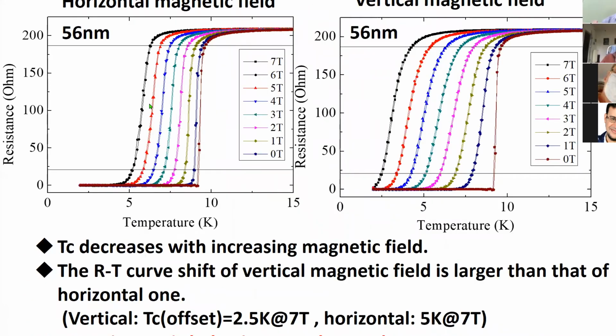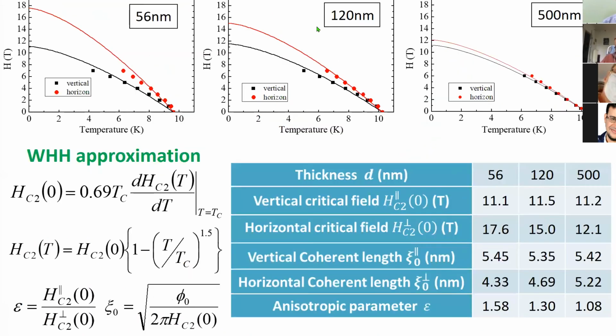So we also measured some anisotropic upper critical field, where the superconductivity stops. With a horizontal magnetic field and a vertical magnetic field, you can see when we change the magnetic field, TC, the transition temperature, goes down. But this tendency differs between the vertical and horizontal magnetic field. We call this anisotropy taking place, and we measured vertical and horizontal magnetic fields and saw the different HC2 points here and here.